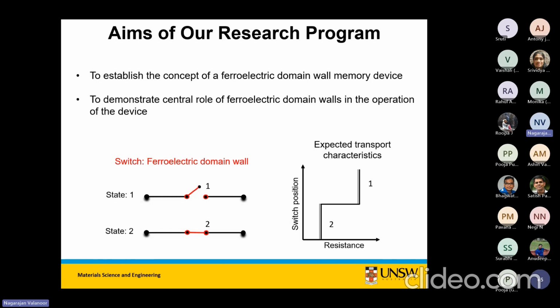In a very simple design concept, the wall is there. It is, let's say, 1. I erase the wall, it's a 0. Okay. Now, easier said than done. It's not so straightforward to get these conducting domain walls in other ferroelectrics, but with bismuth ferrite, for a number of reasons, we have this very beautiful system where one set of walls conduct and the other one doesn't. Which means if you know how to grow bismuth ferrite well with the desired walls, we can start to think of this memory structure.